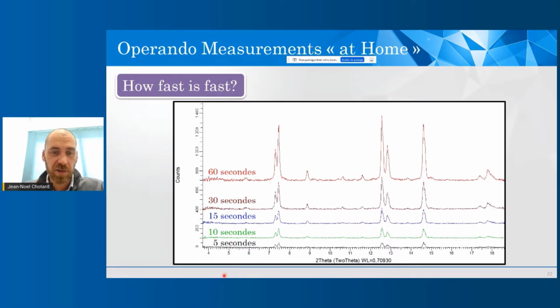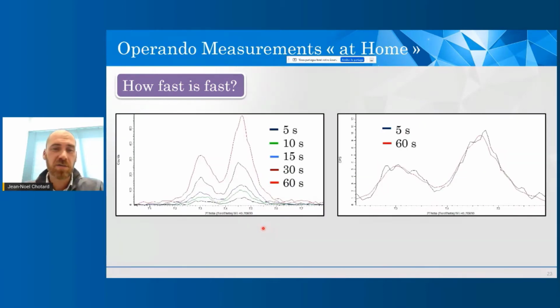can see here with the black powder pattern. Of course, if you superimpose everything, we are losing quite a lot of intensities when the time is decreasing. But if we normalize, we see that it's much more noisy when you have just a 5-second scan. But still, we can definitely see the position of the peaks, and we are able to follow the peak position changes during the cycling. And it's just in a 5-second scan. So that's really, really fast.